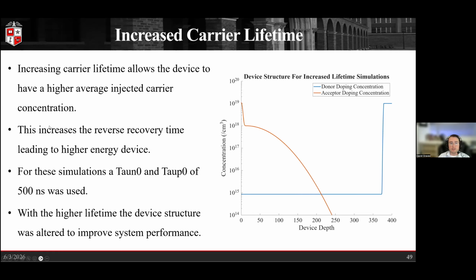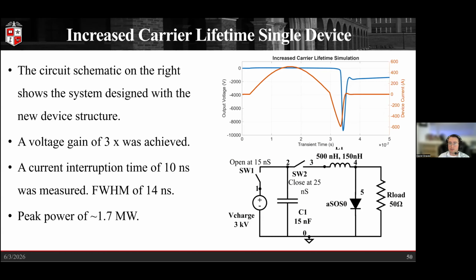But that basically will increase the carrier lifetime, allowing us to have a higher injected carrier concentration. And this increases the reverse recovery time, meaning we can store more energy in our inductor, leading to higher energy systems. And so by adjusting our tau n naught and tau p naught to 500 nanoseconds, and then optimizing the device structure slightly, we can see some different results here.